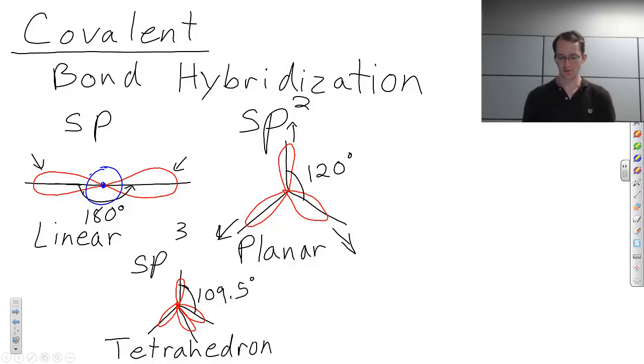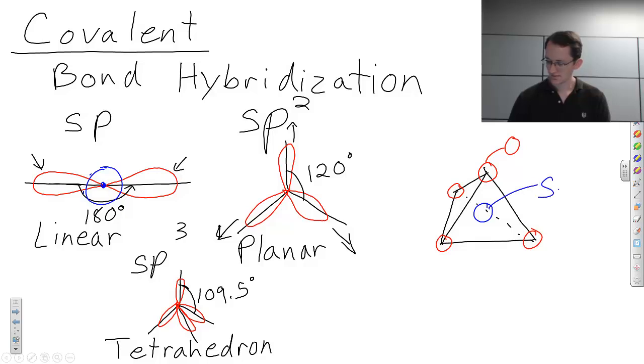And if you don't know what a tetrahedron is, just look it up online and it'll be able to tell you. So a common material that creates these sp3 kind of bond hybridization is silicate. And silicates are all around us. It's a very common material. And so what happens is, we have this kind of tetrahedron like this. And we have oxygen atoms on the outside and a silicon atom on the inside. Oxygen, silicon. Now the silicon is creating this sp3 bond hybridization. And it will bond with oxygen covalently. And you have this very distinct tetrahedron created because of that directional bonding.